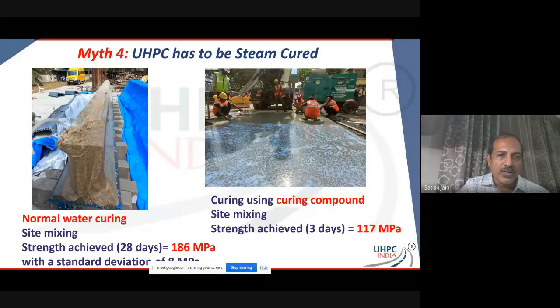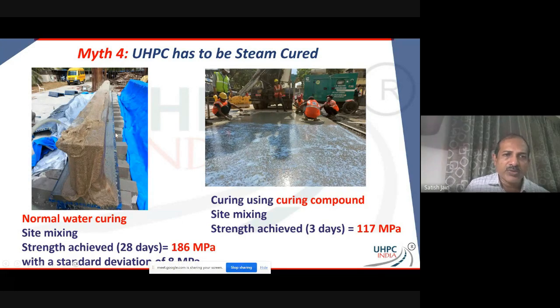And then there is another myth saying that UHPC has to be steam cured. Again, I'll tell you, for 90%, 95% of UHPC, there is no need to steam cure it. You can just use your normal curing. You can use your curing compound. On the left side, these are small UHPC beams, about 8.5 meters long. Over 30 days UHPC was poured continuously, about 84 beams were put together, and you can see the strength that was achieved. We took cubes every day. Site mixing, normal water curing, mean strength of 186 MPa with a standard deviation of about 8 MPa.